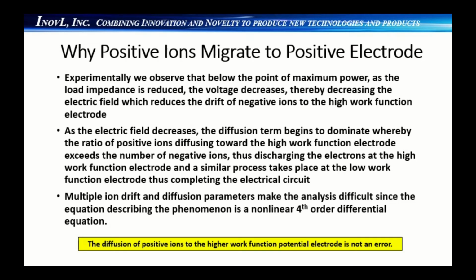This slide provides a brief explanation of why positive ions will diffuse to the positive electrode. Experimentally, we observe that as the load resistance is decreased from very high, which is essentially open circuit, to very low, which is approximately short circuit, the current and power both initially increase. However, at some point the power peaks and then it declines as the load resistance is further reduced, but the current essentially remains relatively constant.